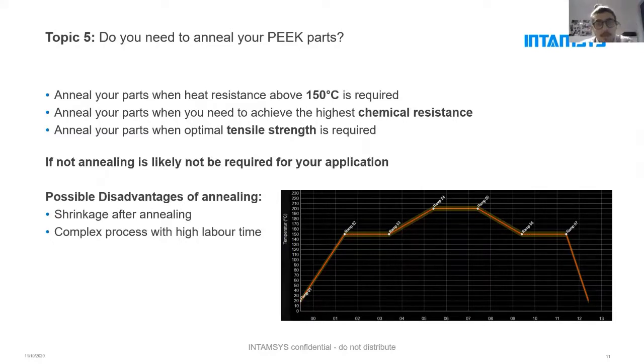And this is something that I would definitely avoid. As we print with amorphous strategy, we discuss a lot about whether I need to anneal my PEEK parts. There are three points that you need to ask yourself to know if you need to anneal or if you may not require that. The first is: anneal your parts when heat resistance above 150 degrees Celsius is required. If you have an amorphous part and you go above 150 degrees, you have the risk that your part only slightly crystallizes. You definitely get deformation, while you have no control over how fast you heat it up and so on. So this is definitely a maximum for amorphous parts.